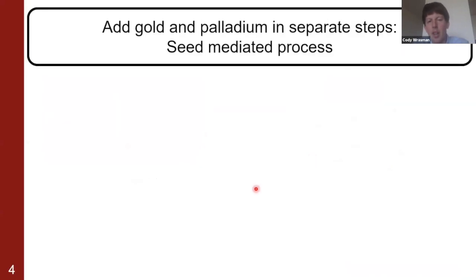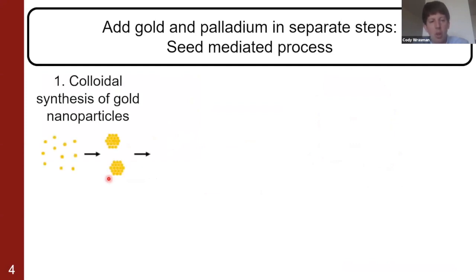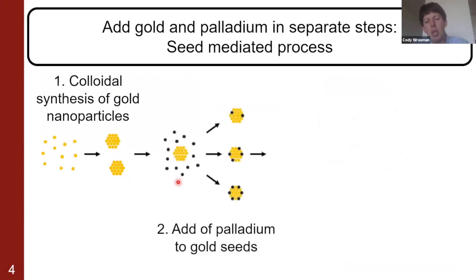Specifically with this palladium gold nanoparticle synthesis, we used what's called a seed-mediated process. So first we used colloidal synthesis to make gold nanoparticles. I think you guys talked a little bit about the cool properties of gold nanoparticles yesterday. We could then take those gold nanoparticles, add them to a different synthesis with controlled amounts of palladium, such that very, very small amounts of palladium could be added to the gold nanoparticles, such that we had these geometries that look something like this.